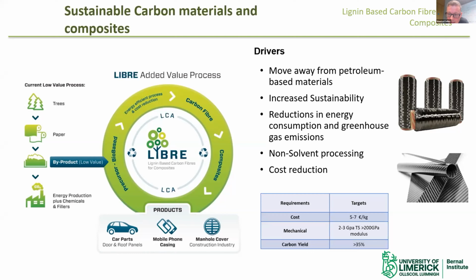Uniquely as well is that we scaled this fiber to TRL 4 or 5. And then we converted this precursor fiber to carbon fiber, and we converted it using conventional processes, which involves using conventional ovens, furnaces, where you heat the precursor to 1,000 degrees C and it gets carbonized. And we also converted it using a low energy microwave technology, which I'll talk to you about in a couple of minutes. So that carbon fiber then was put into a polymer matrix, and it produced a composite material. And those composites were then used to make demonstrator parts.